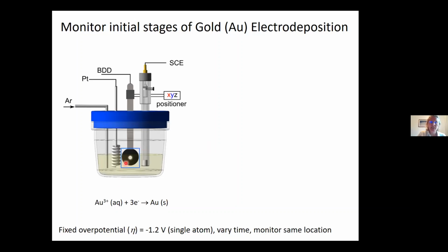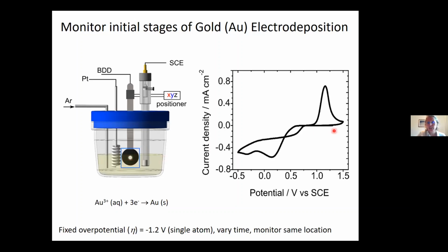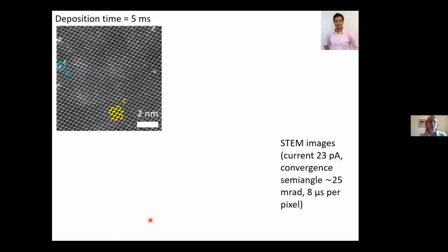So we dip our BDD grid into the solution. We can record electrodeposition CVs, and we can decide what potential we want to hold at for what time. For all the studies I'm going to describe, we use high overpotentials in order to create very small, presumably stable nuclei and a high density of nuclei. So let me show you what we do. So I'm just putting up a picture here of Hatham, because he's been instrumental in driving all of the work that we've done on metal deposition on these TEM substrates.